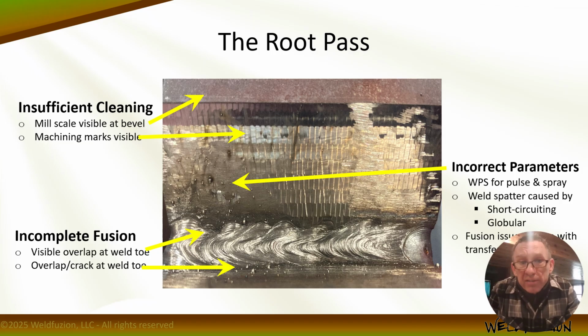Incorrect parameters did definitely result in globular short-circuiting transfer that contributed to fusion issues and launched spatter all over the weld face. And I noted that spatter was not removed prior to being covered up. And when you have molten spatter landing on solidified material around the weld, it's an area of lack of fusion. And if you cover it up, you're going to bury that lack of fusion down inside the material. So good practices are required to get good joints.